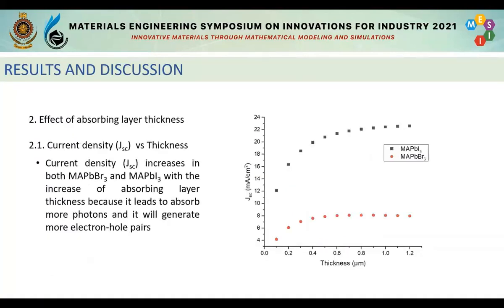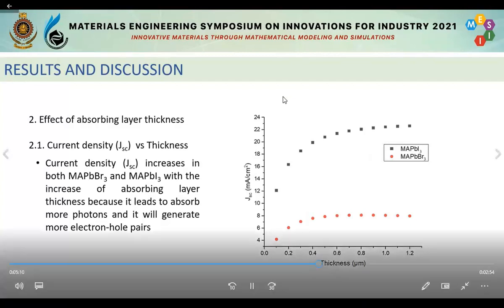When considering the effect of the absorption layer thickness, current density increases in both methylammonium lead bromide and methylammonium lead iodide with the increase of absorption layer thickness, because it leads to absorbing more photons and it will generate more electron-hole pairs.